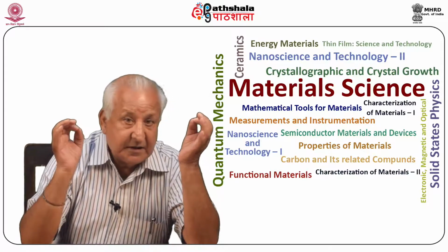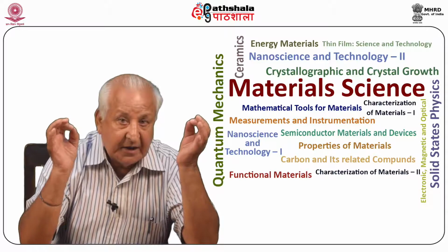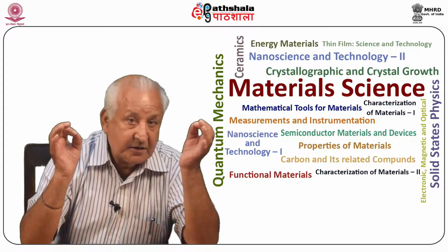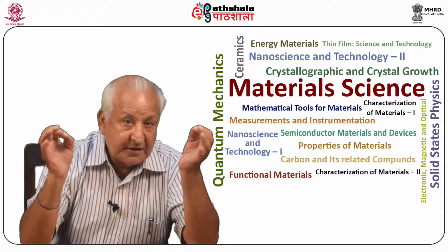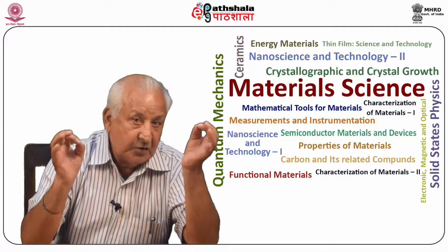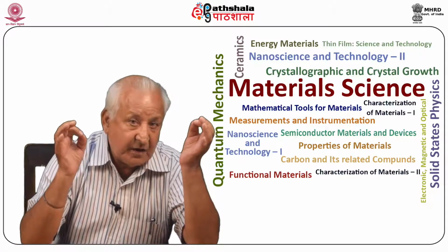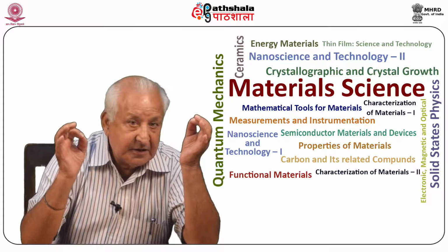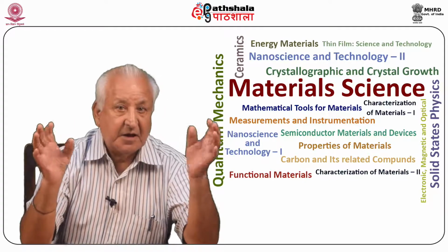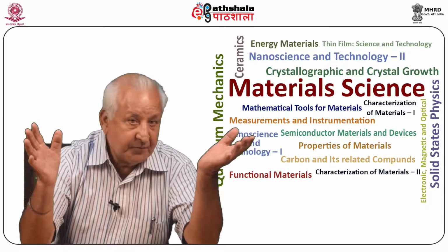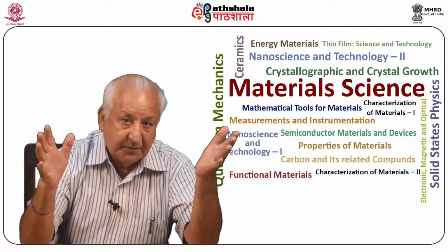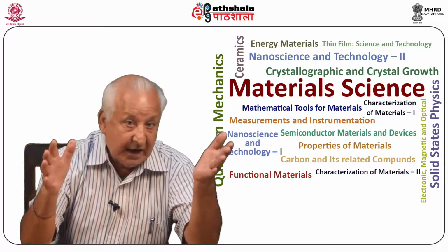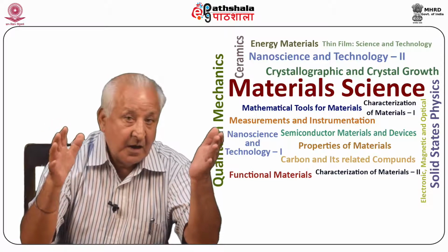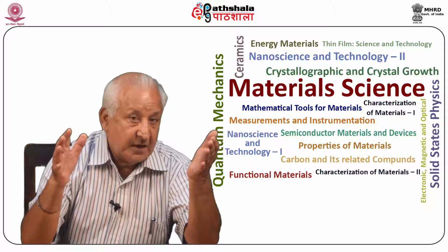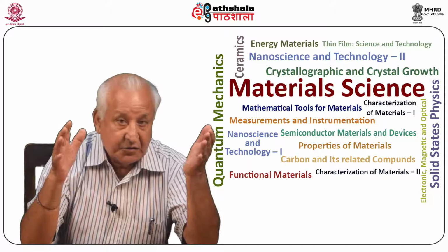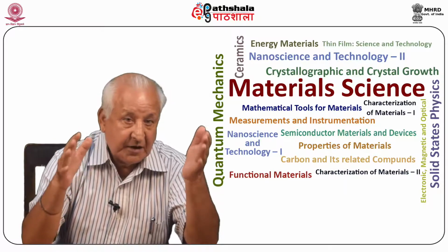Now P is the center of the circle and PQ is the line joining the reciprocal lattice point to the center of the circle. PQ is parallel to the direction of reflection OM. It means that the lattice planes are appropriately oriented for Bragg diffraction if their reciprocal lattice point lies on the circle of reflection. The direction of diffraction is given by the line joining the origin to the reciprocal lattice point.